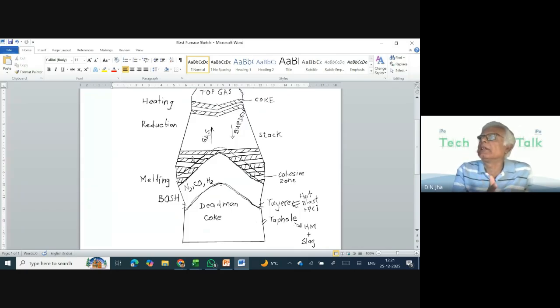It will exchange heat. So once I say that this exchanges heat, that means the burden gets heated at the bottom. Whatever burden that we have, that gets heated to the maximum. As the gas ascends up, because it has lost heat, the temperature at the top will be much lower than the temperature at the bottom. The burden is coming down, and therefore this is the first thing, that the burden gets heated. The temperature at the top is the minimum, and the temperature goes on going up as the burden is descending. So is that understood?